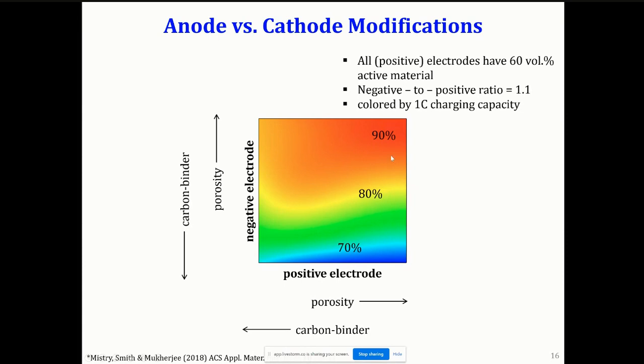And the colors that I'm showing you are the capacity that you get normalized by the maximum theoretical capacity at 1C. You can see that increasing porosity and decreasing carbon binder helps you improve this capacity. And each of the electrodes has a different effect. Your negative electrode has a much stronger effect on improving the performance of this cell rather than making changes on the positive electrode. So going back and looking at what are the essential resistance spots lets you systematically change the things that are most hurtful.